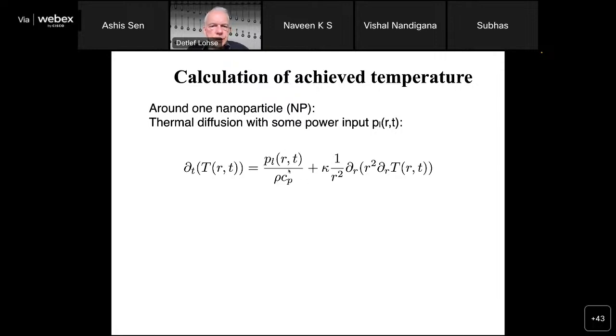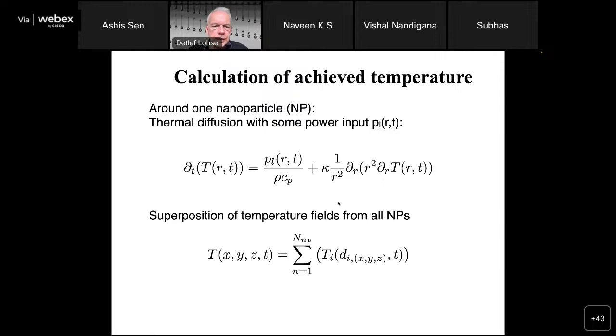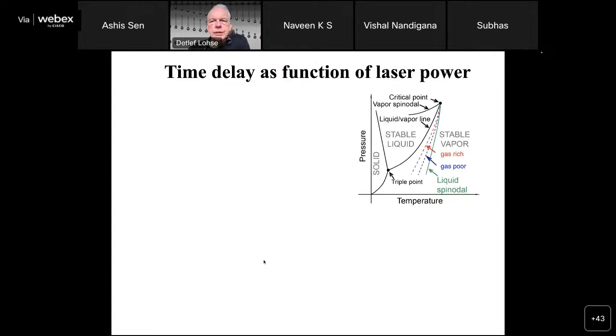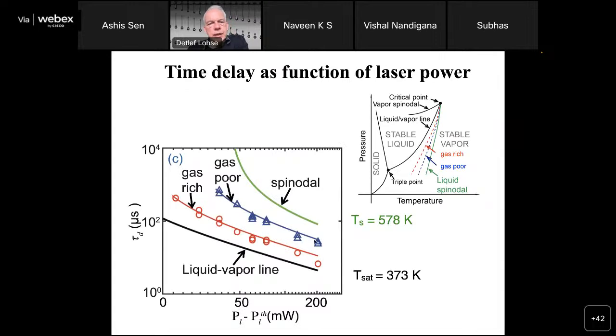We have the sources here, the nanoparticles, and we have thermal diffusion of this power around these particles. We superpose the temperature fields from all nanoparticles, and we can reconstruct the temperature field. And out of this, we can then calculate the curves and reconstruct the temperature. So here is the delay time as a function of the power. This is the liquid-vapor line, which corresponds to 100 degrees Celsius. The spinodal curve is up here, but those two curves which we measure are in between, and out of this we can in fact calculate the temperature with this trick.